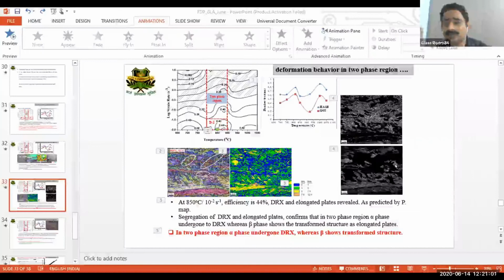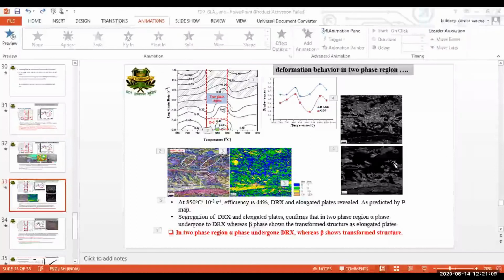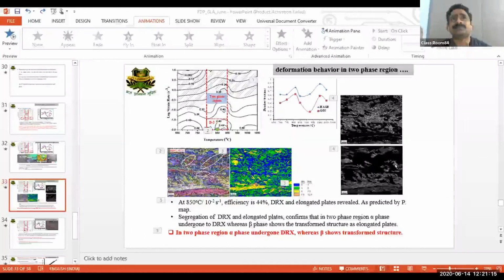Very good question. And I asked the same question to some expert, I think 6 or 7 years back. When you move ahead after 50% of deformation, that is 0.69 true strain, your flow curve is almost in steady state nature. So if you are deforming more than this 50% of deformation, usually the material behaves in a similar nature. So people normally deform up to 50%, because whatever changes may exist, they will exist up to 50%.